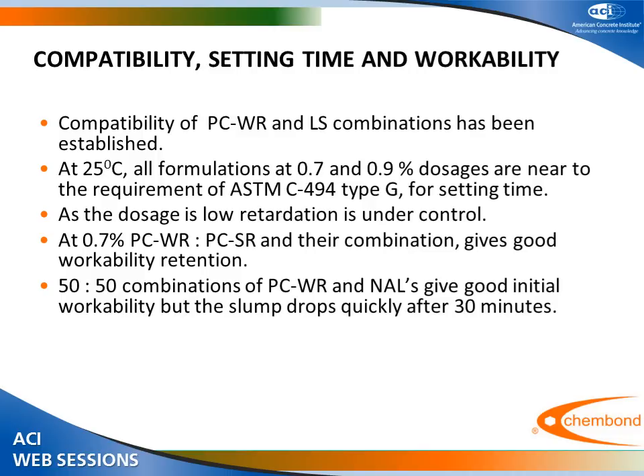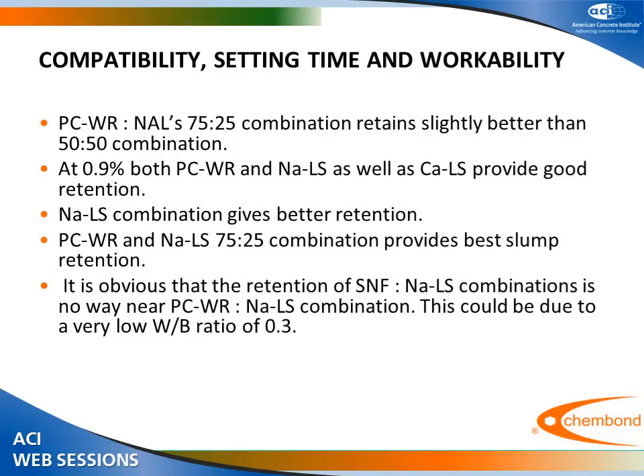Whereas the 50-50 combination of PCWR and sodium lignosulfonate has given good initial workability, but the slump drops quickly after 30 minutes. This is for the 0.7%. Then again, the PCWR and NALS combination 75-25 retains slightly better than the 50-50 combination. At 0.9%, both PCWR and sodium lignosulfonate as well as calcium lignosulfonate have provided good retention. Sodium lignosulfonate combinations of course are better than the calcium lignosulfonate combination. PCWR and sodium lignosulfonate combinations of 75-25 have given better slump retention.